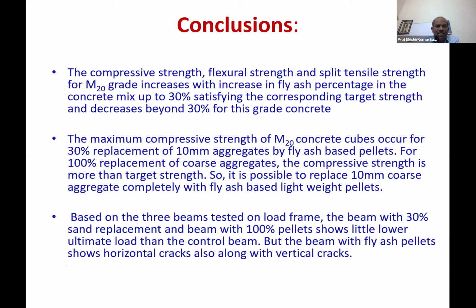Based on the 3 beams tested on the load frame, the beam with sand replacement and the beam with 100% pellets show little difference in ultimate load from the control beam, but the beam with fly ash pellets shows horizontal cracks along with vertical cracks.